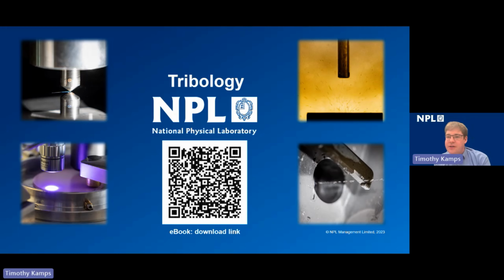And if there are no more questions, then we might have reached the end. Oh, okay, yes. The question is, you mentioned solid particle erosion at the beginning of the talk. Can you expand on the capability in this area? So yeah, on the slide you can see here at the top right we've got solid particle erosion. This is gas-borne solid particle erosion, and we have two pieces of equipment at NPL that can do this. One of them at high temperature and high speed, and one of them at room temperature and slightly slower speed. So slightly slower speeds up to sort of 90 meters a second, higher speeds up to 220 to 250 meters a second, and high temperature up to 800 degrees.